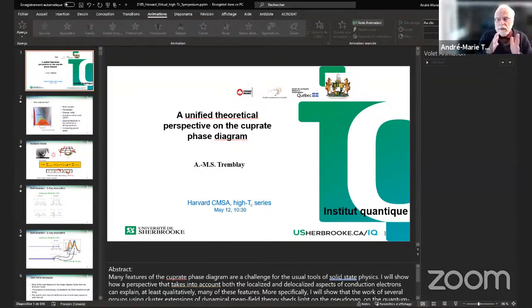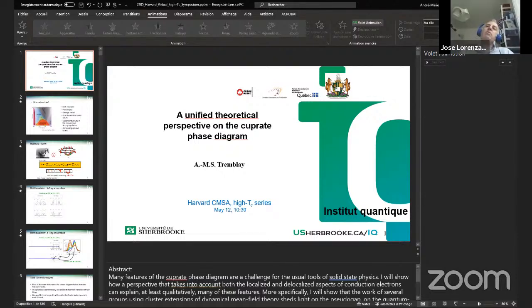It turns out in the 3-band model, there are still some transitions, and there are some experiments that suggest that, by Sakuto, for example, with Raman scattering. But at least in the 1-band model, once you go into the superconducting state, what's left of this first order transition is this crossover from kinetic energy dominated condensation energy to potential energy dominated condensation energy. So in that case, it's just a crossover. But if you remove the superconductivity, you see the first order transition in the normal state. So if you remove superconductivity, you would expect to see a phase separation or some inhomogeneities. So there is somehow competition between inhomogeneities and uniform superconductivity.